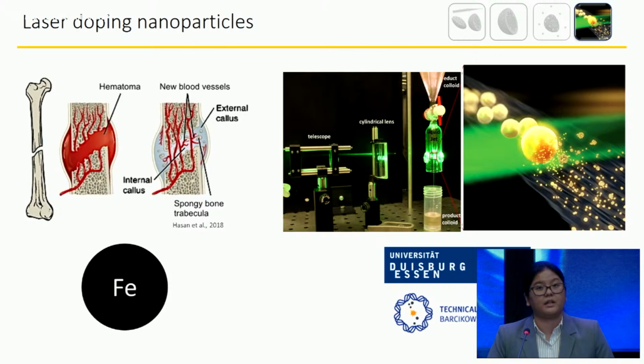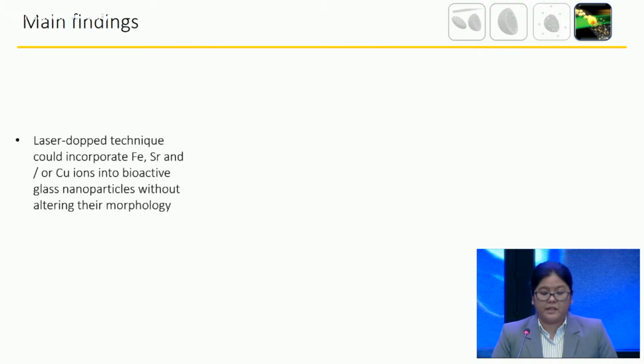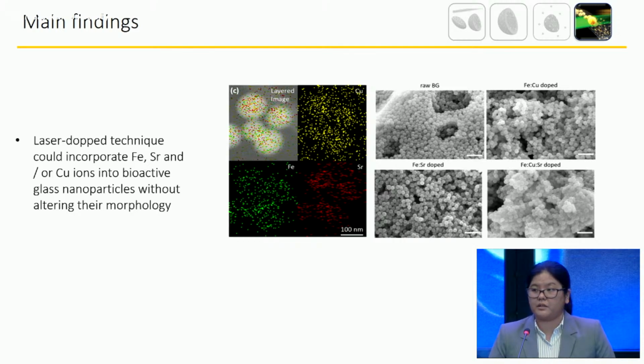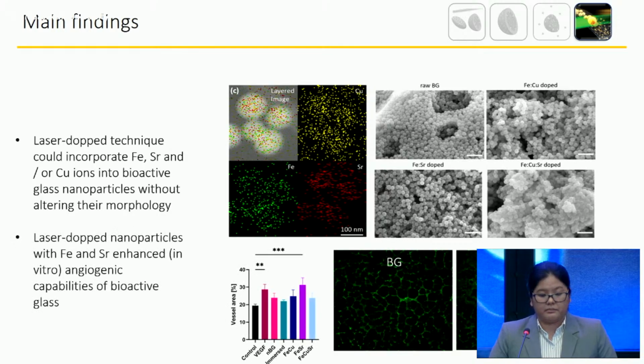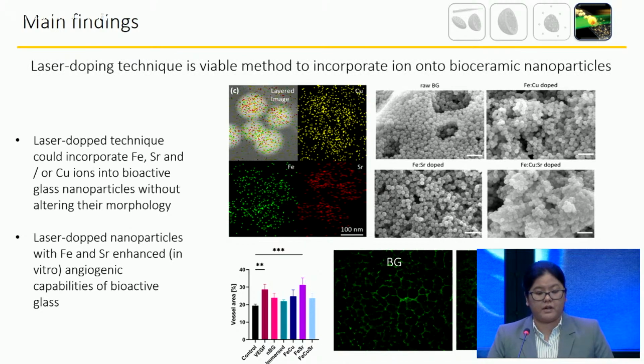After processing, the laser-doped nanoparticle's capacity to induce osteogenic differentiation in HMSC and angiogenesis vessel formation in human umbilical vein endothelial cells was evaluated. The laser doping could successfully incorporate three ions, strontium, iron, and copper, into the solid bioactive glass nanoparticle without affecting their morphology and size. Albeit in low quantity, the multiple ion incorporated bioactive glass nanoparticle had significantly higher osteogenic activity compared to the non-doped counterpart. Therefore, the laser doping technique is a viable method to incorporate ions onto the bioceramic nanoparticle.